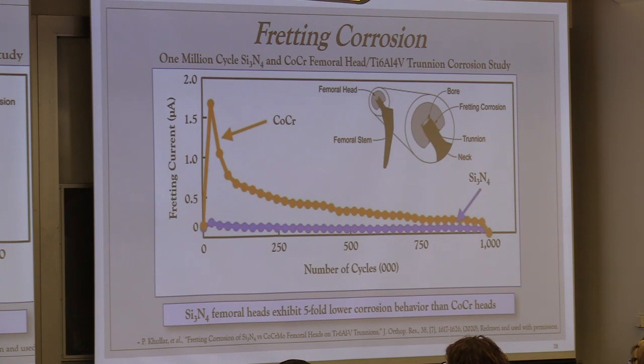And lastly, the most current problem that exists out there in terms of the reason people are going to ceramic over metals is fretting corrosion. So if you have a particular femoral head that's, in this case, a metal, cobalt chrome on a titanium stem, you have an electrochemical couple here between these two, and with slight pressure and motion, you get actually fretting corrosion that occurs, and that fretting corrosion products actually fall into the joint space and create all sorts of problems, including pseudotumors, what's called metallosis. I've seen operations where they open up the patient's hip and leg, and there's a great big pseudotumor there that's on the order of an orange or a grapefruit, that they have to pull out. And so this is a major problem.